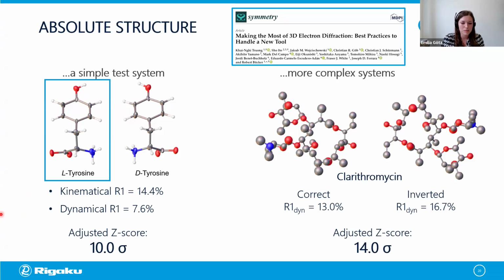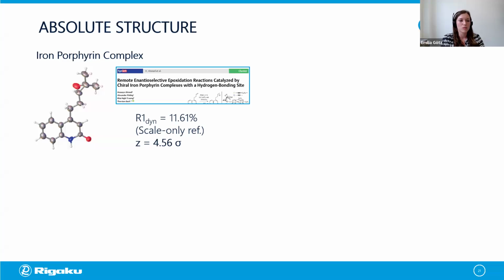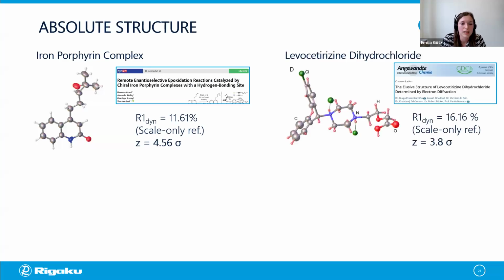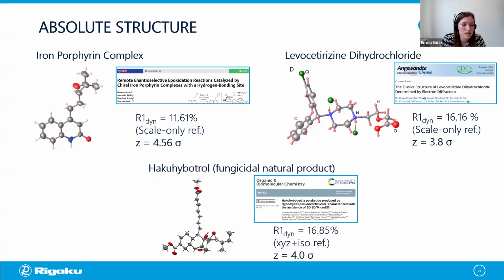Even on more complex systems, such as clarithromycin, we managed to get a high Z-score. Here we can also see the difference between the R values of the correct and inverted structure, but in some cases, this difference might not be as large. So it's really good to have another value to go by. And here are some more published structures which were refined dynamically to get the absolute configuration. Here we have an iron porphyrin complex, an API, and a fungicidal product. And in all cases, the Z-scores are above 3 sigma. And in the first two cases, it was even sufficient to only refine the scale. And here, atom coordinates and ADPs were refined as well.